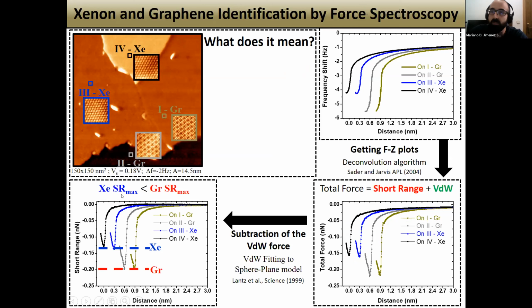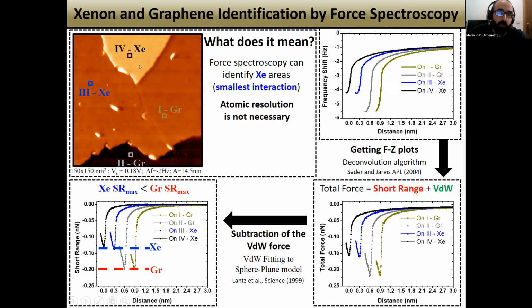And what does it mean? Well, it means that if we have an overview image like this, and we perform force spectroscopy in each of the different regions, just by looking at the maximum attractive force, we can distinguish xenon from graphene. I mean, the lower interacting area will be the xenon region. Then we don't need atomic resolved images to distinguish xenon from graphene.